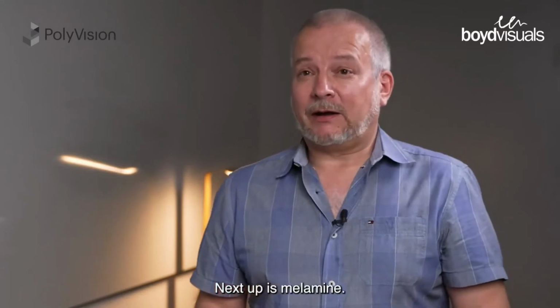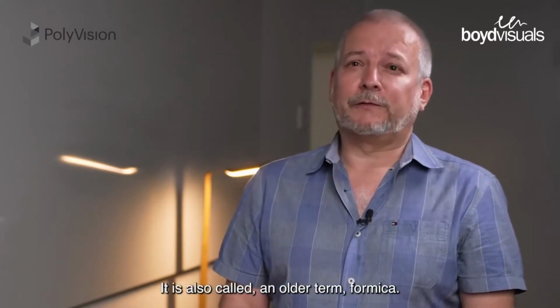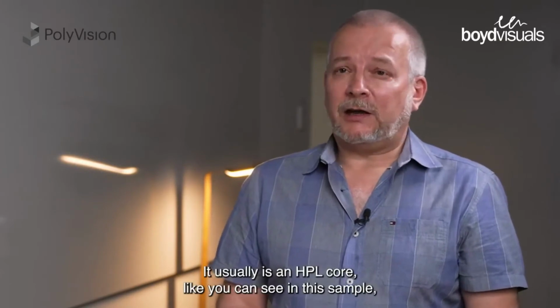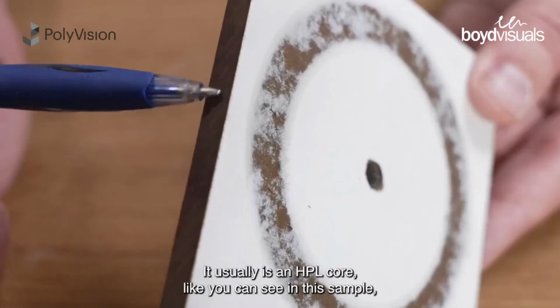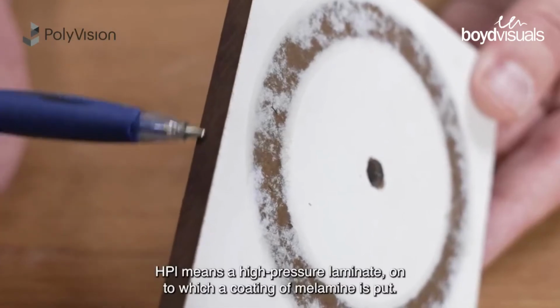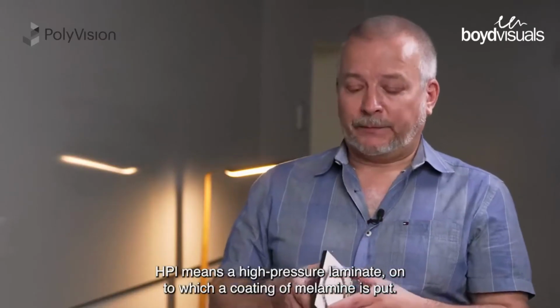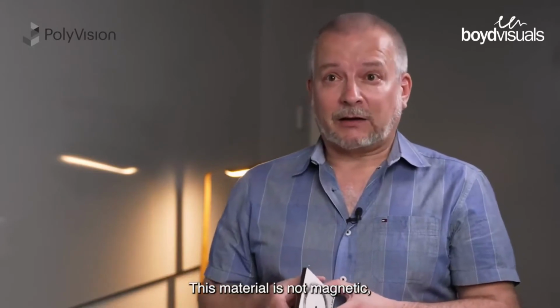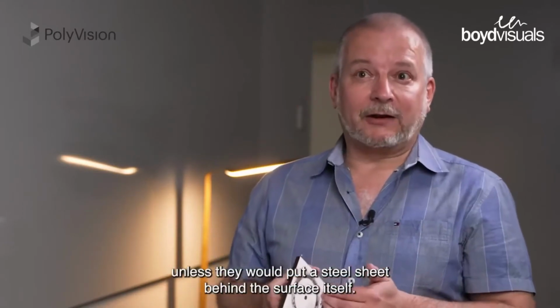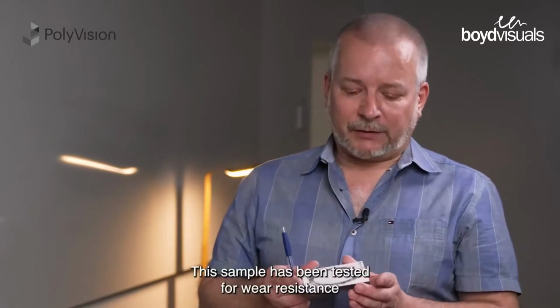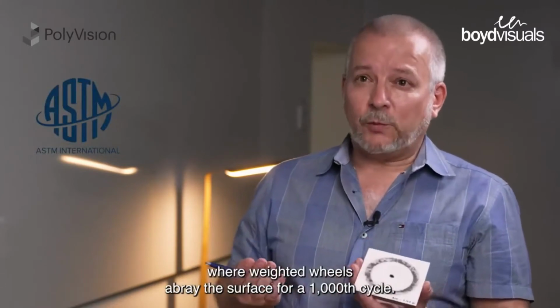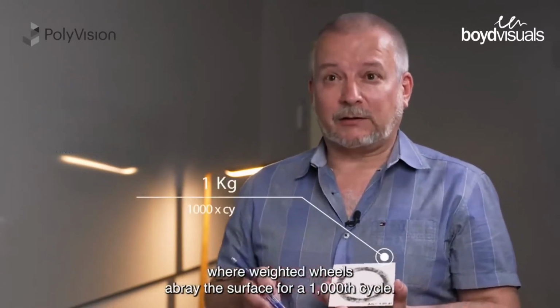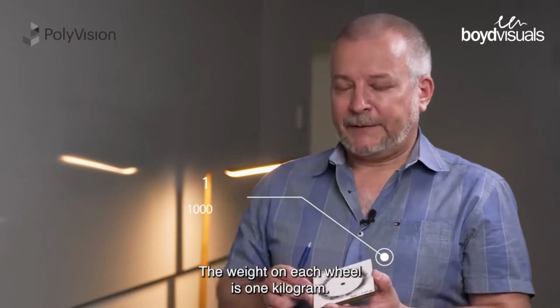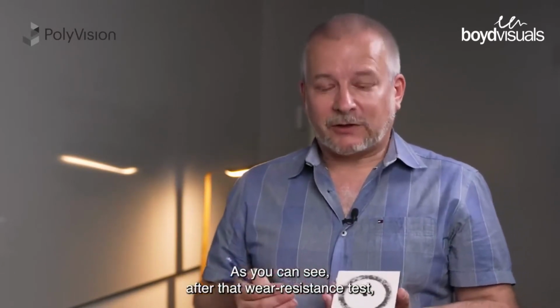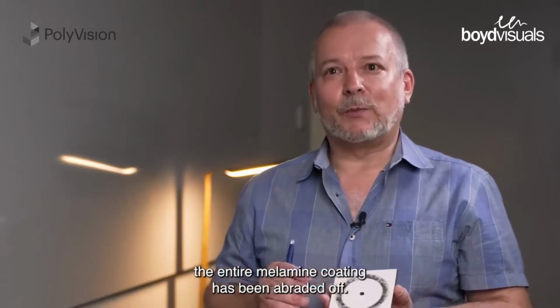Next up is melamine. It is also known by the older term formica. It usually is an HPL core, like you can see in this sample. An HPL means a high pressure laminate onto which a coating of melamine is put. This material is not magnetic unless they would put a steel sheet behind the surface itself. This sample has been tested for wear resistance according to an ASTM international standard, where weighted wheels abrade the surface for 1,000 cycles and the weight on each wheel is 1 kilogram. And as you can see, after that wear resistance test, the entire melamine coating has been abraded off.